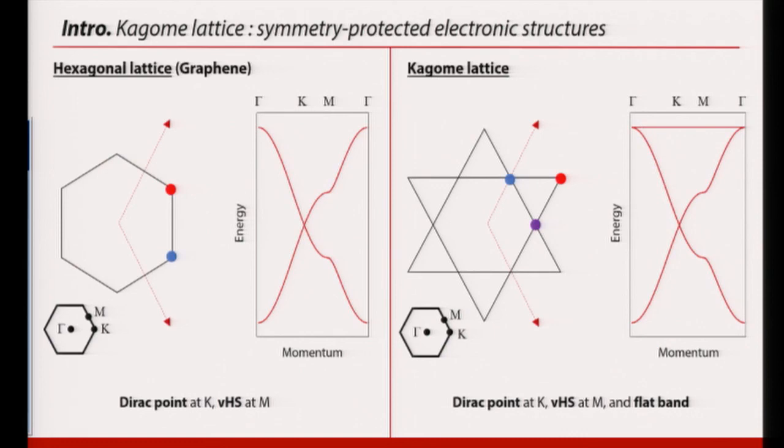Most importantly, for the Kagome lattice, here you see a representation of this hexagon, a six-pointed star type shape, with the 3 atoms that form the unit cell in the Kagome lattice. This tiling of the 2D plane has the same point symmetries as graphene. So there is a close connection to the hexagonal lattice. In fact, you can map one onto the other, and you can think of the Kagome lattice as basically an extension of the hexagonal lattice, which you form by adding 1 additional atom in the unit cell.